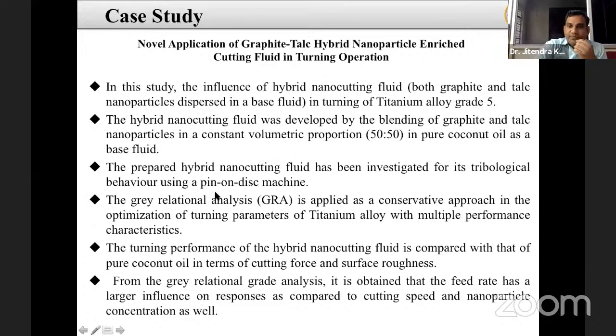The hybrid nano cutting fluid that I have studied, I also studied its tribological behavior on a pin-on-disk machine. With three parameters at three levels, we made a Taguchi analysis, then performed ANOVA and grey relational analysis to obtain the operating parameters. We also compared the results with pure coconut oil in terms of cutting forces and surface roughness.